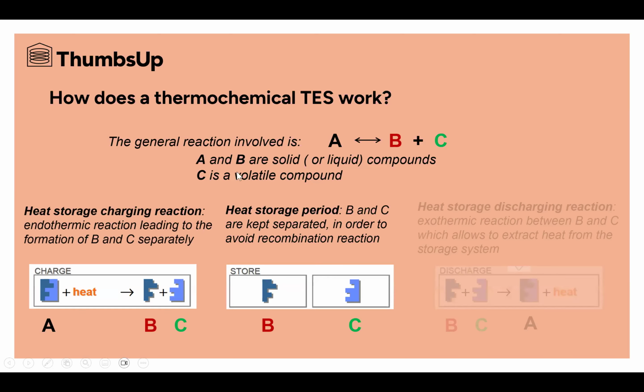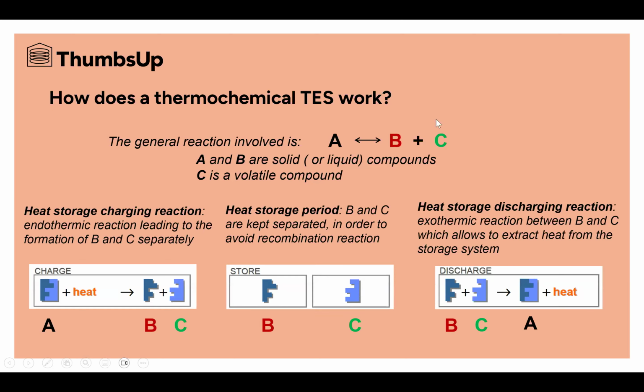So this reaction is structured in three phases. Heat storage charging reaction: we have an endothermic reaction leading to formation of B and C separately. Heat storage period, where B and C are kept separated in order to avoid the recombination reaction. And the heat storage discharging reaction, which is an exothermic reaction between B and C, which allows us to extract heat from the storage system.